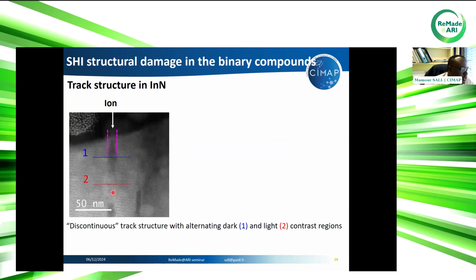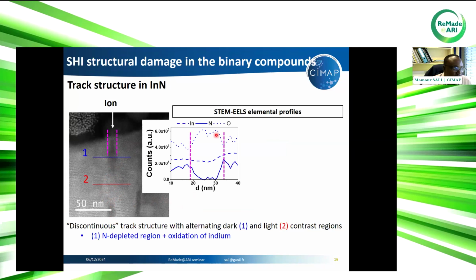So when we look at the track in the volume, it's made of alternating regions. We have this dark region here and light contrast region here. And this is the same, if we look deeper in the sample, we will have the same structure. So we perform, again, chemical analysis using STEM-EELS measurement. So first, we record the elemental profile measurement in position 1, so in the dark region, following this line, the blue line. And what we can see here is that in the track, there is a decrease of nitrogen content and an increase of oxygen.